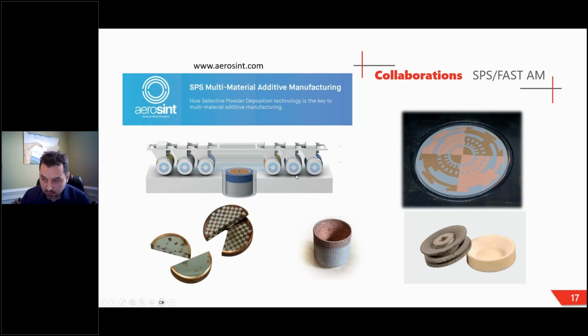In some cases, one of those materials might be a support material that does not sinter to the material, but then is removed later, leaving you with a 3D shape. And in some cases, you get a bit of both, where we can do different materials on top of each other bonded, also in a 3D shape. And so for us, this is a bit of a paradigm shift. It's a great way of being able to lay down very uniform, controlled thin layers, as well as, I mentioned, making intrinsically built cooling channels, heating channels, internal geometries that you couldn't make any other way, but also getting the benefits of SPS for the consolidation.